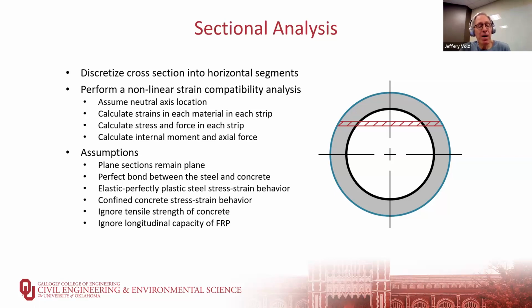We assume a perfect bond between the steel and the concrete. That's the strain compatibility part. Where the concrete touches the steel, they both undergo the exact same strain. There's no slippage. We can use an elastic, perfectly plastic stress strain diagram for the steel, where we have linear stress strain behavior up until yield and then a plateau. We can also make it more refined by including strain hardening if we would want to.